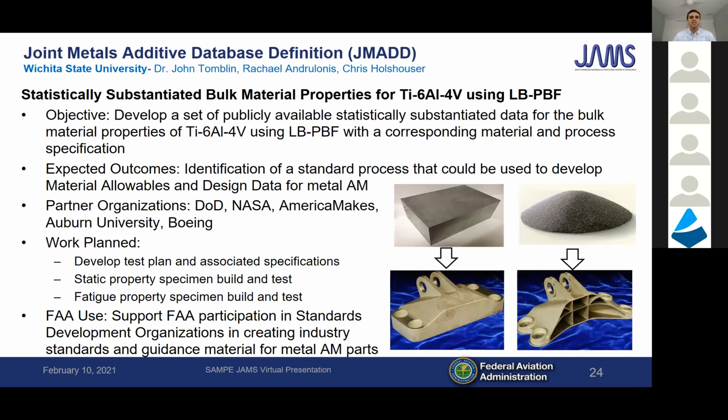of Ti-6-4 metal alloy. The way that powder bed fusion works, essentially the machine spreads a very thin layer of metal powder on a build plate and then uses, in this case, a laser beam as the energy source to melt the powder into the desired shape. That process is repeated over and over again until your full part is complete. Typically, laser powder bed fusion is used for smaller parts due to the limitation of the build chamber size. But the trade-off for size is that it can make very intricate and complicated parts, things featuring internal structures, internal passageways, stuff that can't be done using traditional metal processes.